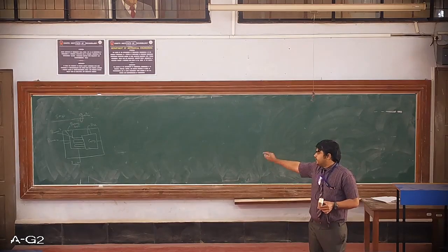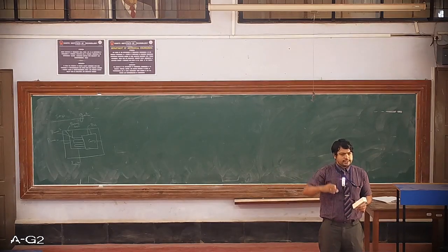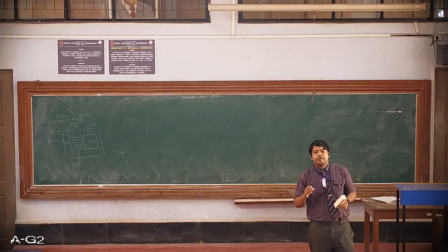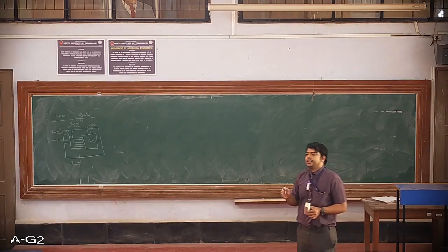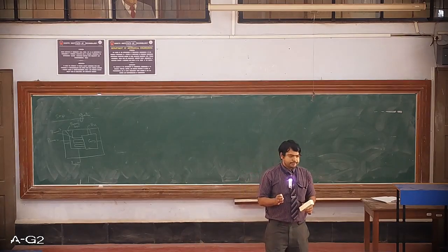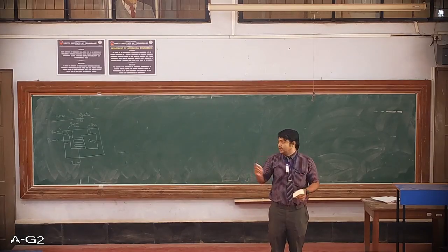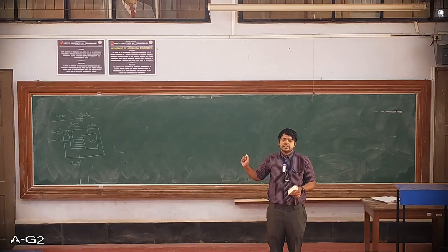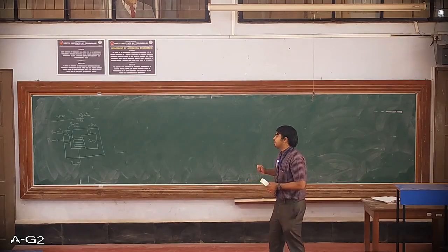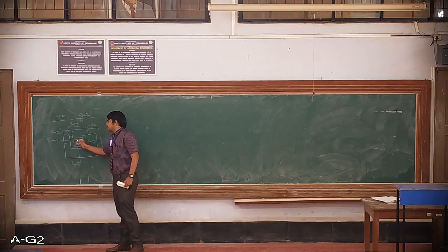There you can see the gates are situated step by step. The cross-sectional area of the bottom gate is smaller. As it goes on increasing, its area also goes on increasing. Okay, this type of gating system is used for heavy castings. It is going to produce a sound casting. Okay, sound casting in the sense a very good quality casting. But the only drawback with this type of gating system is the cost. As we are going to have a number of runners over here, this is all attached to the fettled component.